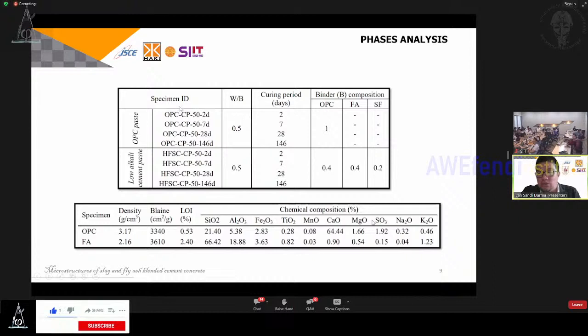For phase analysis of microstructure, here we use synchrotron X-ray CT in Japan. We use cement paste specimens. We use OPC and low alkali cement. In low alkali cement, we use a high volume of fly ash. Here, the water to binder ratio is 0.5, and we cure the specimen for 7 days. And for the fly ash, we use type 2 JIS fly ash.